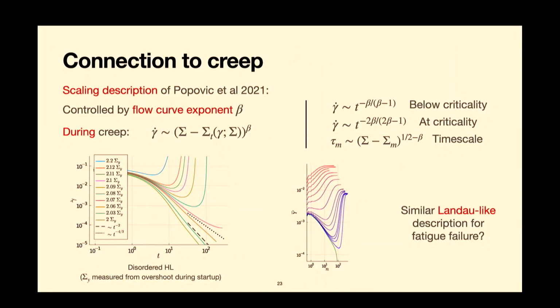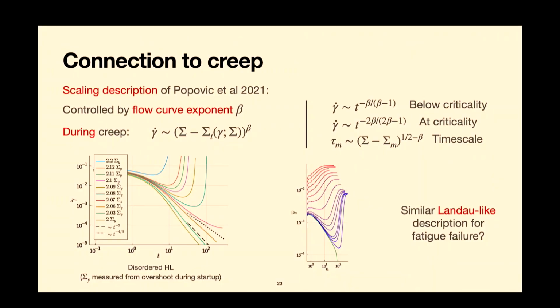And so you can ask a similar question to what we were asking with our oscillatory strain, right? So you can apply this constant stress, which is here called sigma, and then over time you can watch the strain rate. So you can watch how much the system is actually deforming, okay? And you have graphs that actually look temptingly similar to what we had in our system, except we were plotting yield rate, okay, because our strain rate's fixed externally. So it's not exactly the same physics, okay? But here also you have this phenomenon that under creep, the system can basically almost stop moving. The yield rate gets to a very low value, and then eventually you reach a steady state, okay? So there's another interesting question here of whether there's a useful analogy that can be drawn. There's a nice paper from Matthieu Wyart's group where they tried to build a scaling theory of how these curves look. And they get out various scaling exponents for how these curves should look, both at the critical value of the stress, but then also either side of it. Okay.